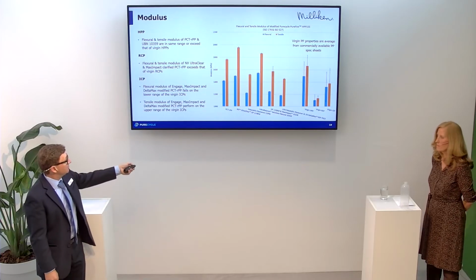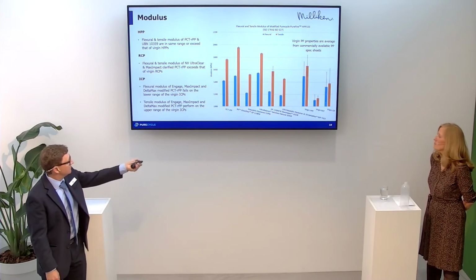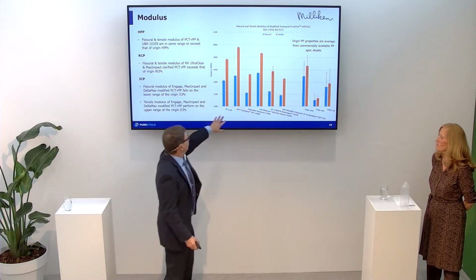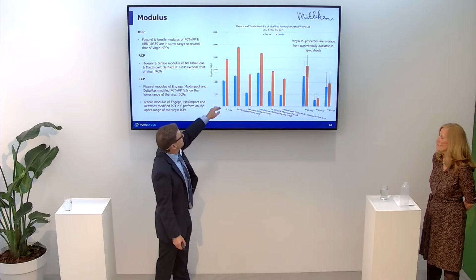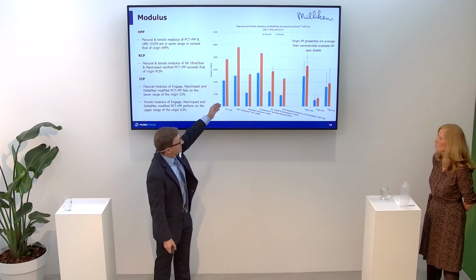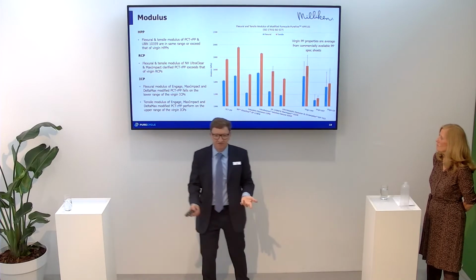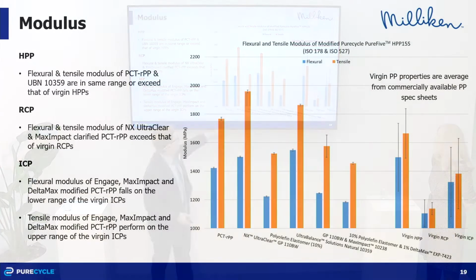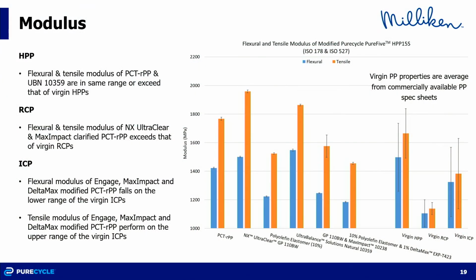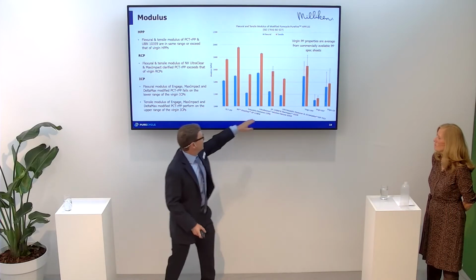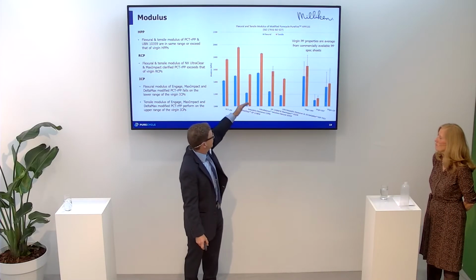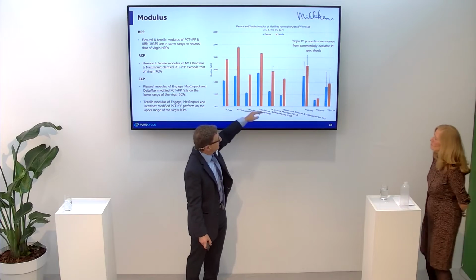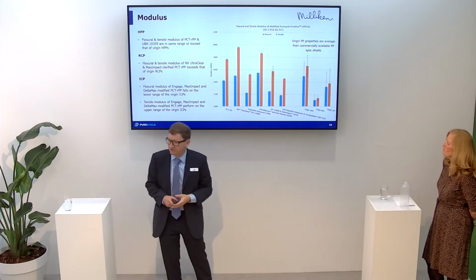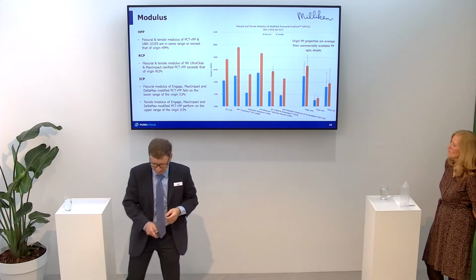So if we look at just their beginning material, keep losing my pointer. So that's the RPP. You can see that the flexural modulus is about 1400 megapascals, which puts it right in the range of a virgin homopolymer. Random copolymers, it's a little higher for the nucleated, so we're about 1500 megapascals, so quite a bit stiffer than a random copolymer. And then by adding the impact solutions, the polyolefin elastomers, you do see a decrease, much like you would see if you add rubber to an impact copolymer.